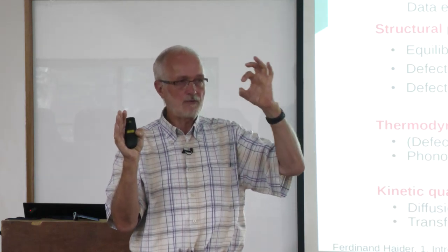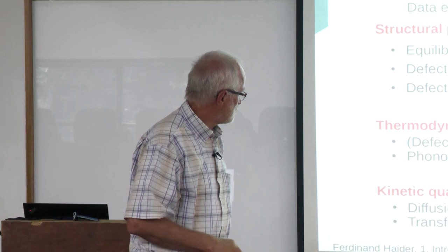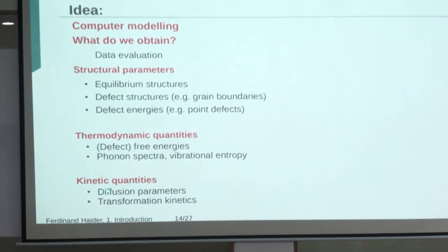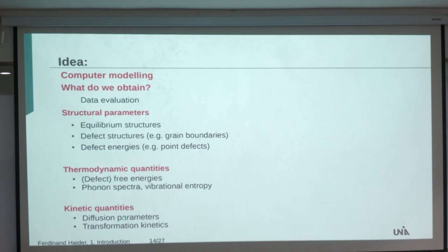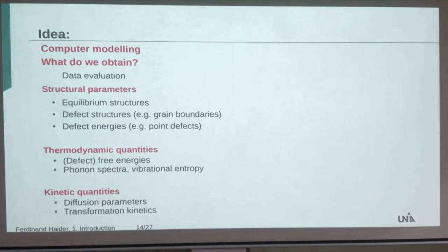Of course, it has a configurational entropy, which one should not confuse, but it also has a vibrational entropy. The atoms perhaps vibrate a bit stronger into the vacant site as they would do in the crystal. These are all things we can get out from MD simulations. And then, as I already mentioned, you can get important input for kinetics.